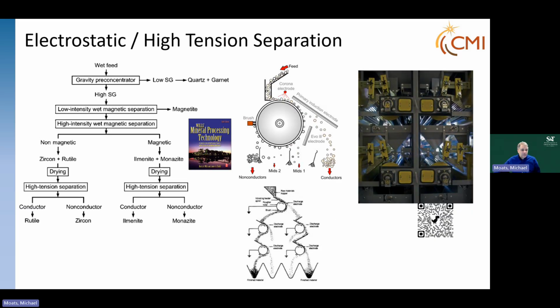Coming out, we've got the gravity concentrators. We get the heavy, higher density materials. We do magnetic separations, and in the non-magnetic fraction, it ends up being your zircon and rutile. You do typically dry them. We don't usually do high tension separations wet.